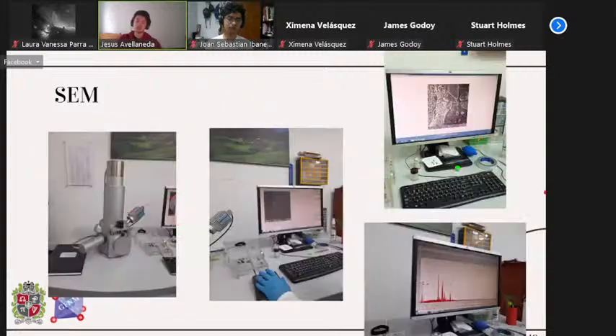But also, complementary measurements were made to help our understanding of the initial XRD results. As you know, there's no single measurement that gives us a complete picture or all the answers that we want when we are studying materials science. As you can see in the following images, this was the machine used. In this case, SEM measurements were taken to carry out surface studies to see how the aggregates of the material were evolving with each thermal process, and also how the grains of said material were evolving with time.